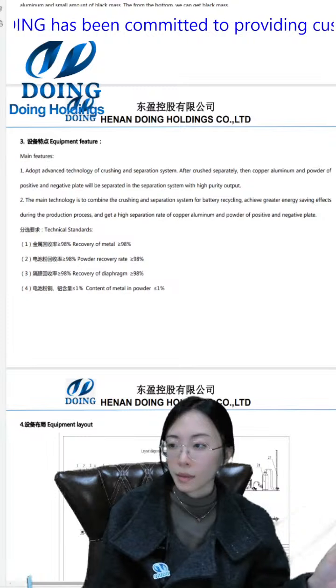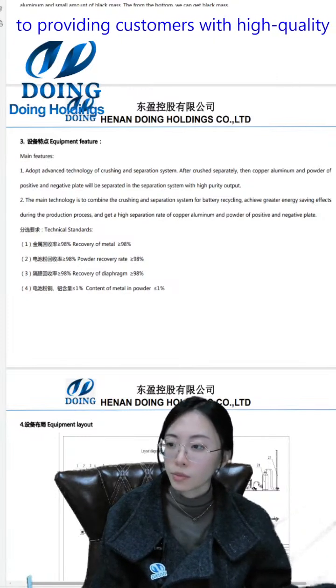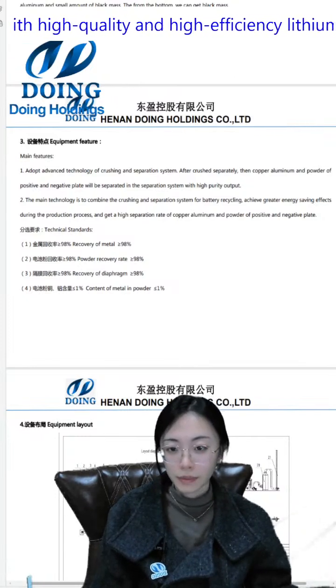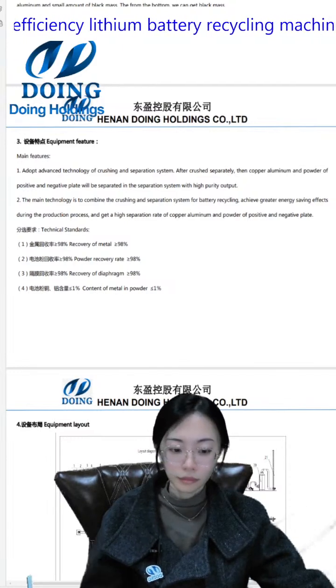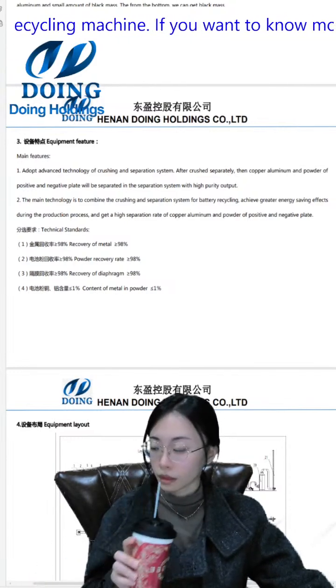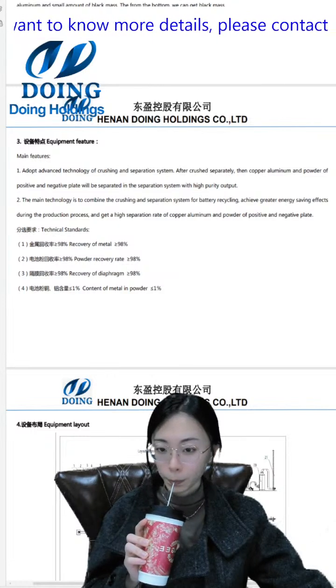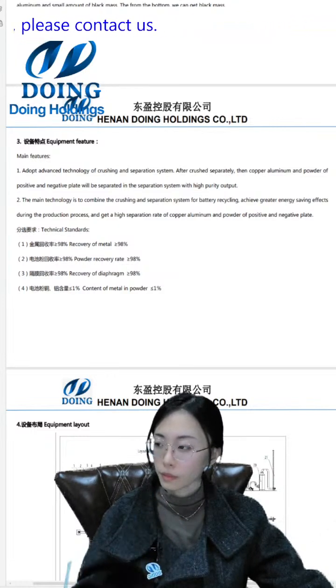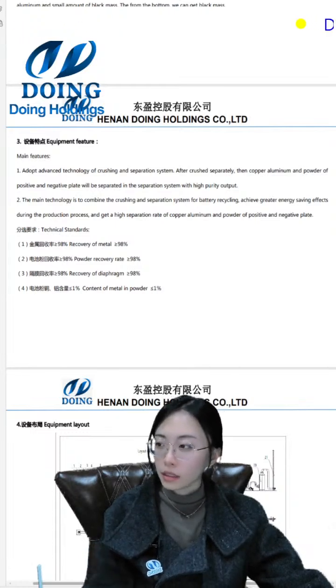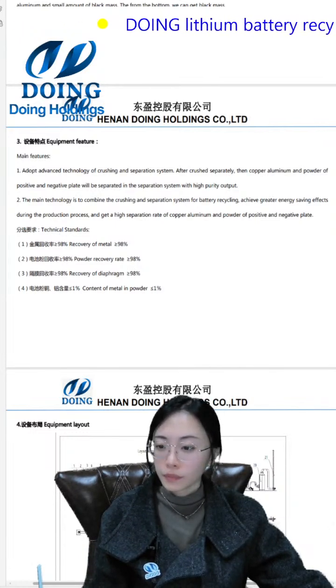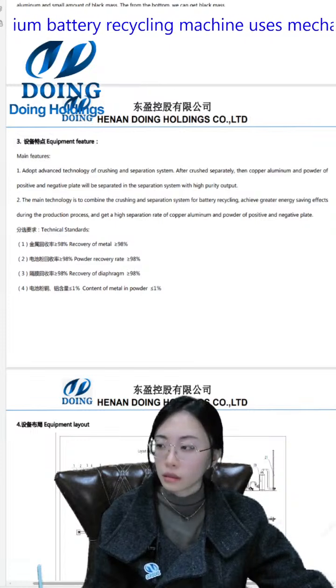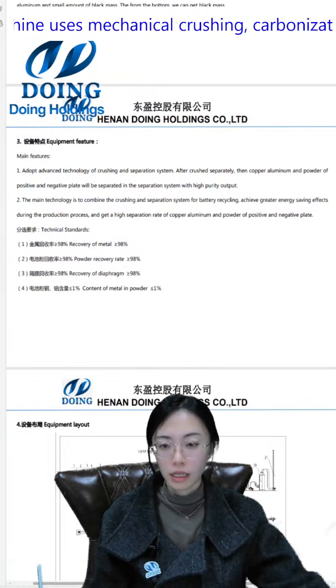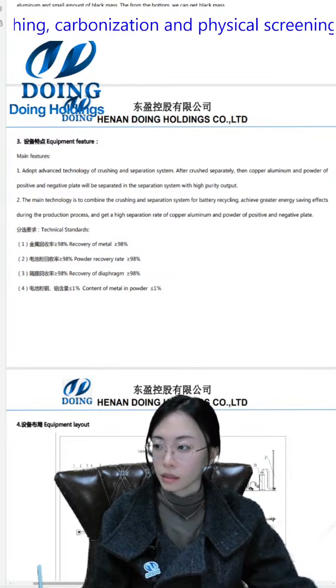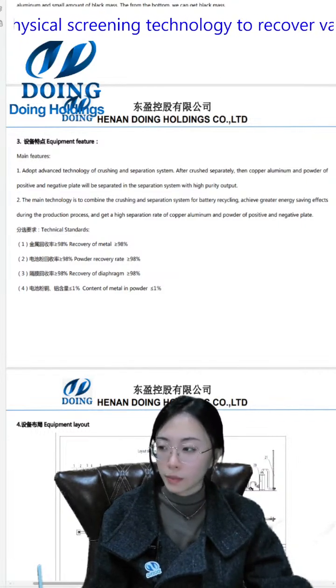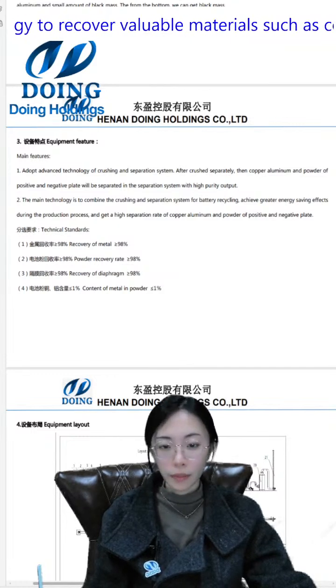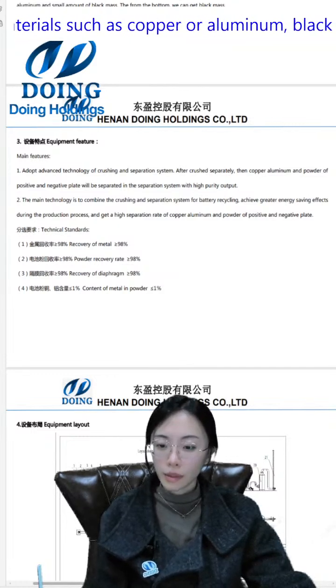That one is the high purity output and the high separating rate. And the technical standard of our equipment. The first one, the recovery of the metals, we can reach 98%. And the powder recovery rate is also 98%. The content of the material in the powder is smaller than 1%.